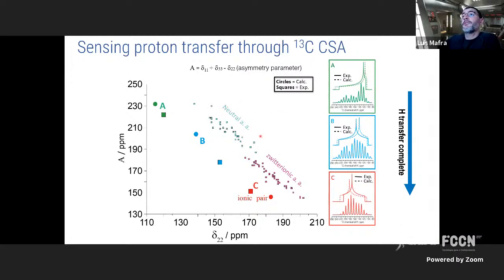We went to a database where we have neutral amino acids and also zwitterionic amino acids, and we put the principal components in this plot, okay? On the y-axis, we took a linear combination of the principal values of the tensor so we can better distinguish the small differences. Here I chose the principal component of the tensor that maximizes differences between protonated and non-protonated amines. Just to be simpler to understand, you have the experimental values in squares and the calculated values in circles. As you see, it fits quite well, in fact. And this corresponds to a proton that has jumped from the carbamic acid to a neighboring amine, okay?